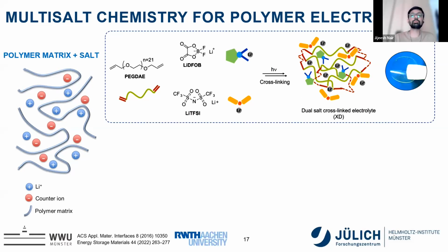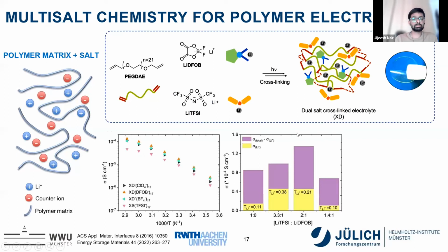So we want to explore this idea and see how it is going to influence. And it was surprising how a single second salt or third salt is influencing the overall electrochemistry of the polymer electrolyte. For example, here you will see that you have a cross monomer, which is PEG-DAE, which is an oligomer, which can be polymerized by UV radiation with a dual salt system, and you can get a very nice cross-link system. Just by